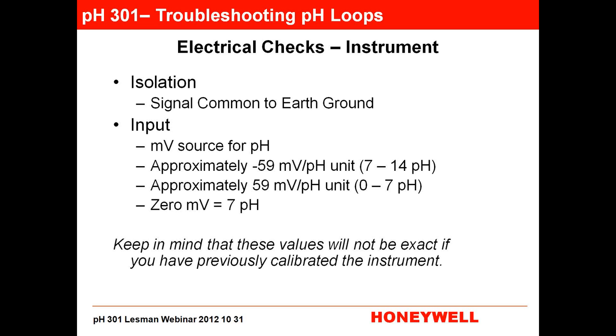you may have put some offset and some slope changes into that instrument by doing calibrations with your sensor. So it wouldn't be exactly 7, but I would think that you would be within like 8/10 to a full pH unit, close to 7, when you put that paper clip across. So, that's an easy, quick trick that you can do just to take a peek at it.